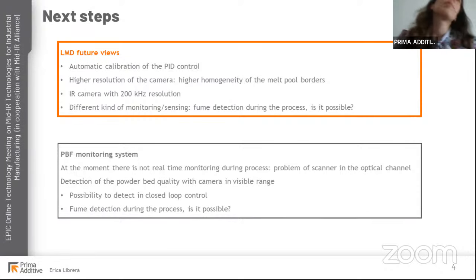But then at the same time, we are looking for something different. For example, a sort of visible system or camera or something that is able to maintain a fixed distance between the nozzle tip and the deposited part. The standoff distance is a critical point in laser metal deposition technology because it generates a sort of instability in the process. One of the most common problems is the presence of underbuilding and overbuilding during the deposition, like in the case of the corners in the square.